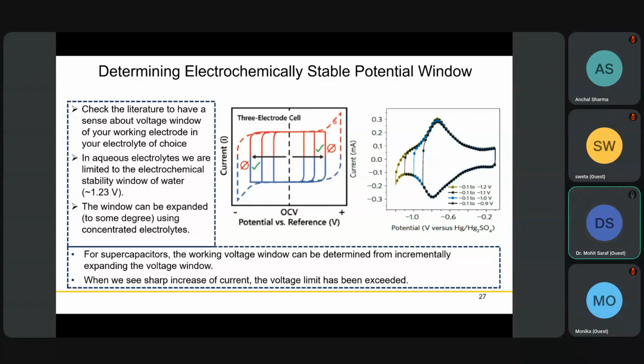Similarly, you do this experiment on the positive side until you see the sharp tail caused by the oxygen evolution reaction. So following this example, your electrochemically stable potential window should be from here to here, and you have to avoid going beyond it. If you take a window like this, in the beginning it's okay that your window looks slightly large and you get high capacitance and energy.